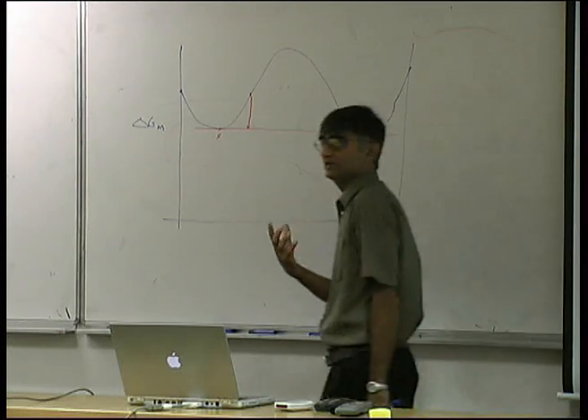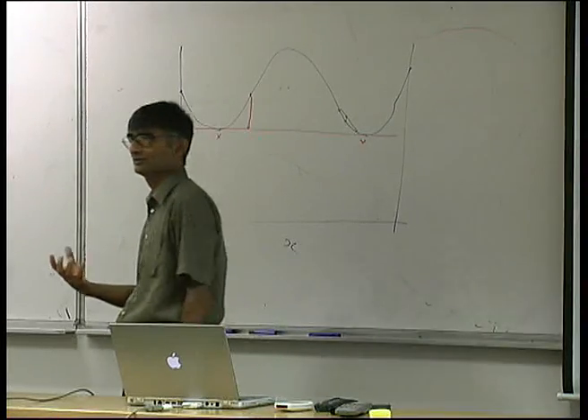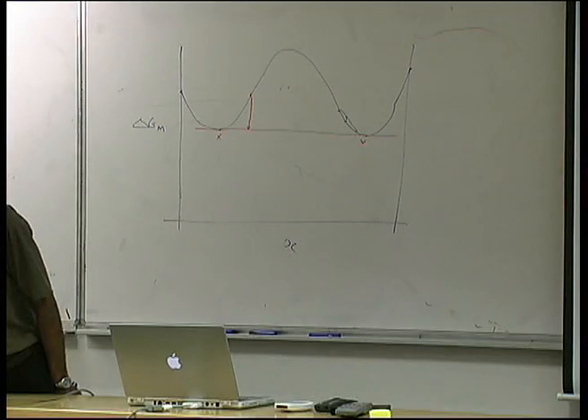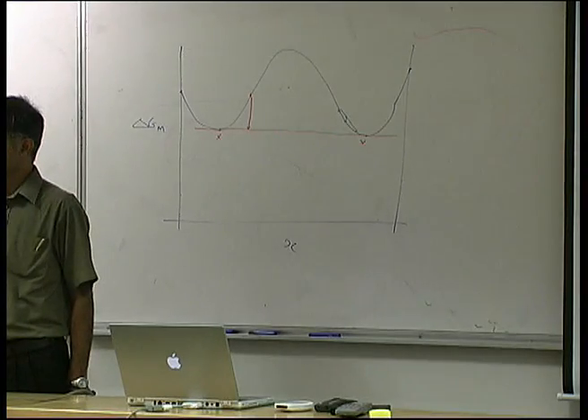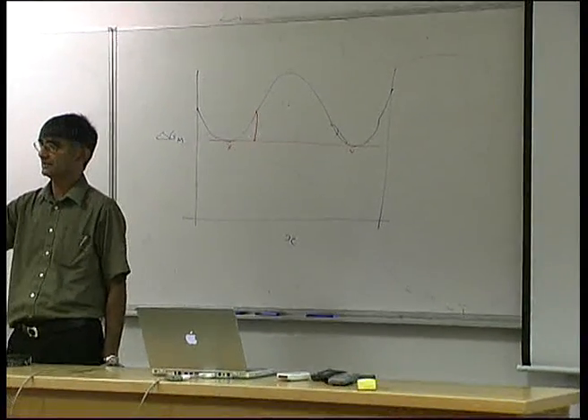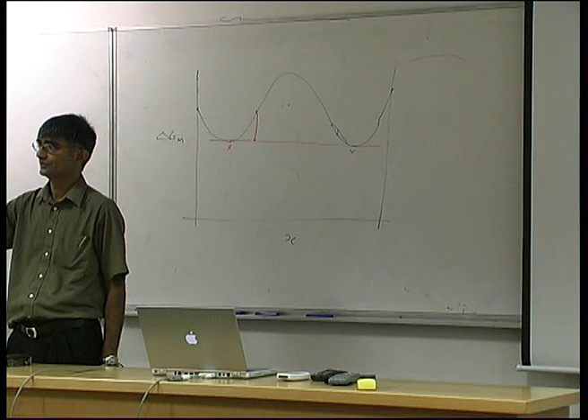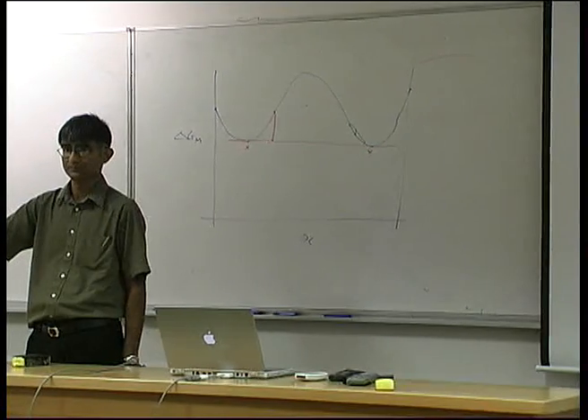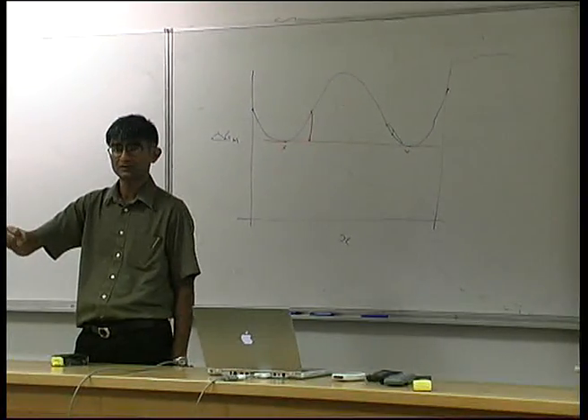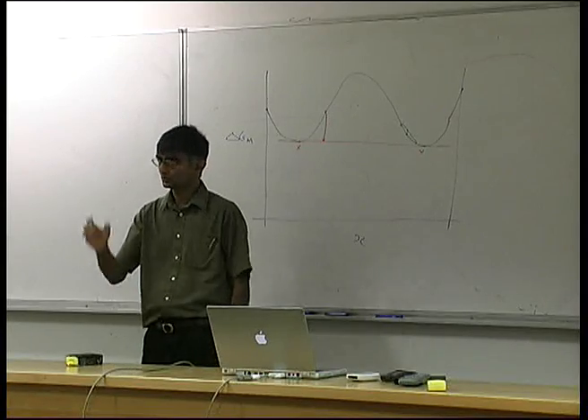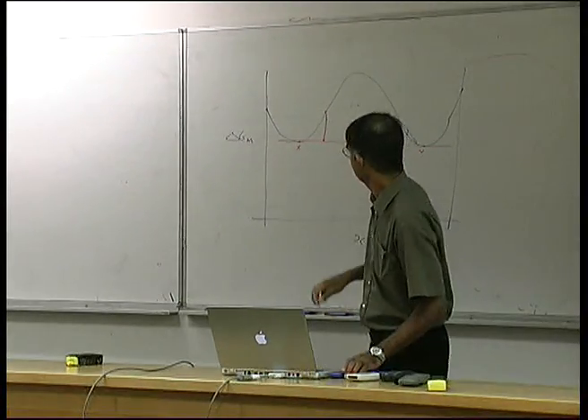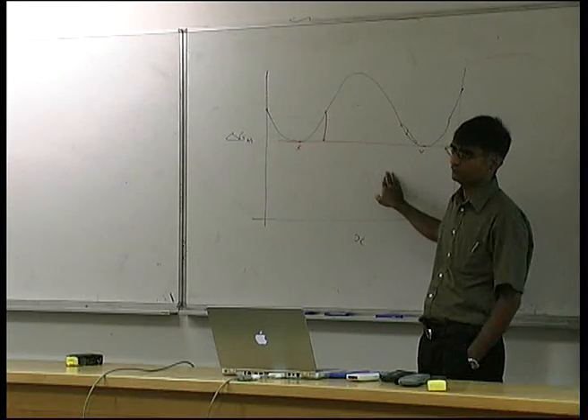That is basically nucleation. Even if there is an overall decrease in free energy when the reaction is completed, you first have to go across a barrier. Because of this curvature, if I put a small perturbation - a disturbance on the homogeneity of that solution - creating a small enrichment of A and a small enrichment of B, I actually get an increase in free energy.